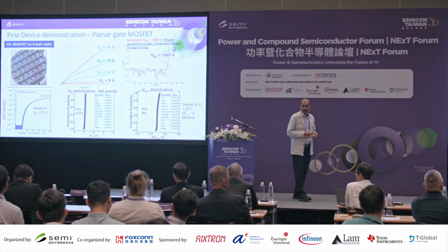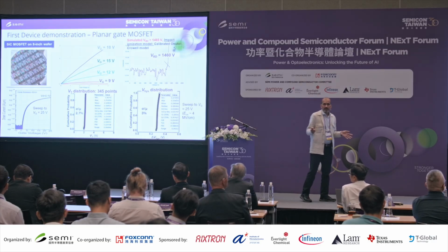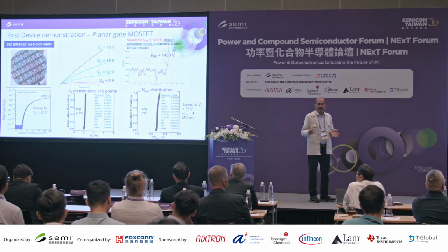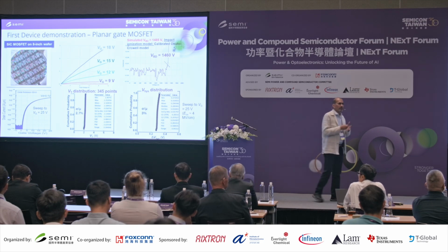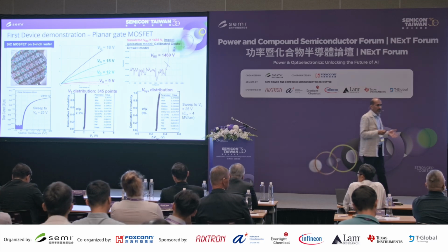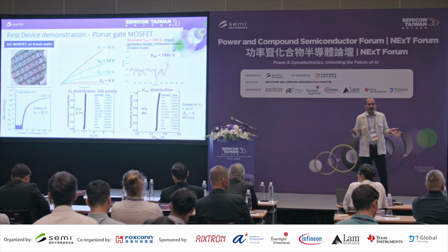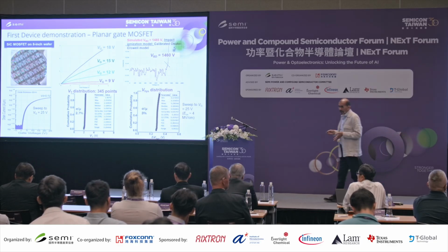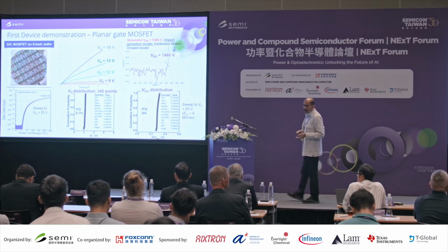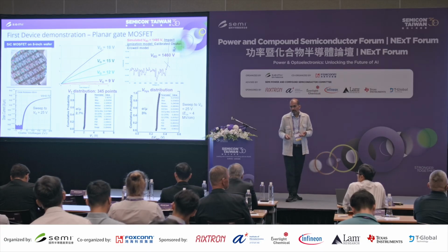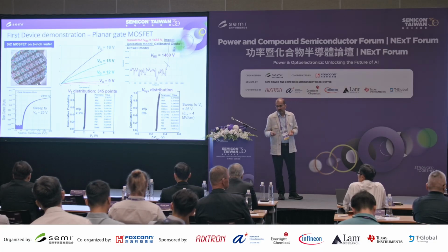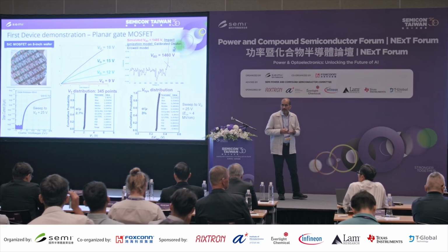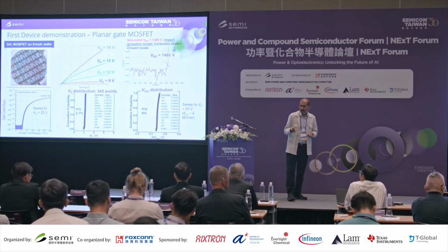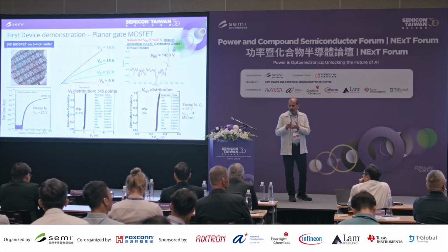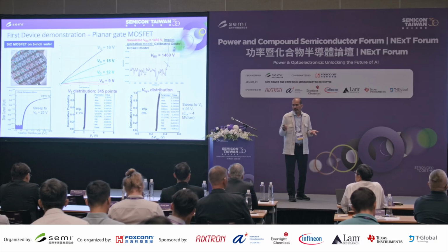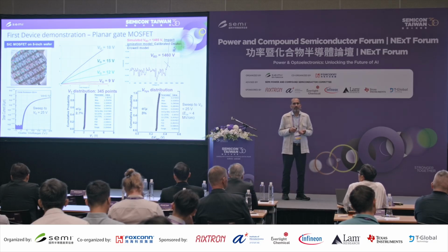MOSFET demonstrations: we fabricated planar devices. We started indeed with planar devices to confirm that our process modules are in good shape, because a planar device is relatively simple. Here is just an example of planar IV characteristics and a breakdown characteristic. So on and off characteristics are both obtained in the same device. And our simulation models are so close. You can see here the real breakdown is 1460 while it was simulated at 1485.